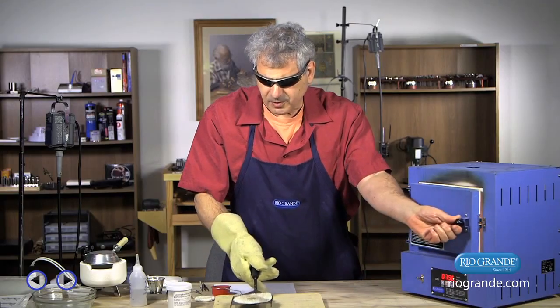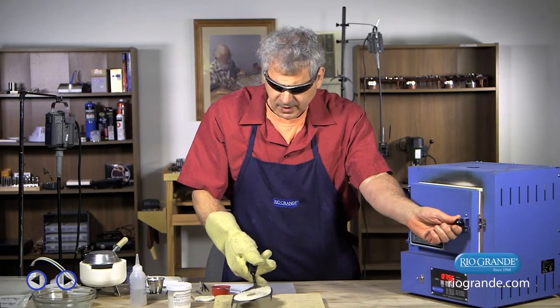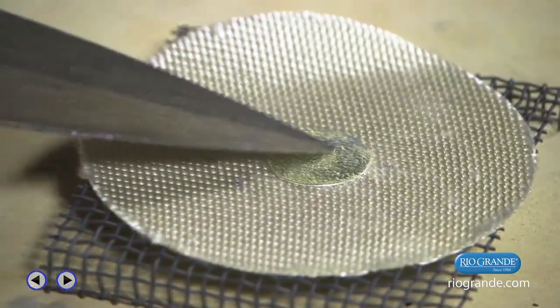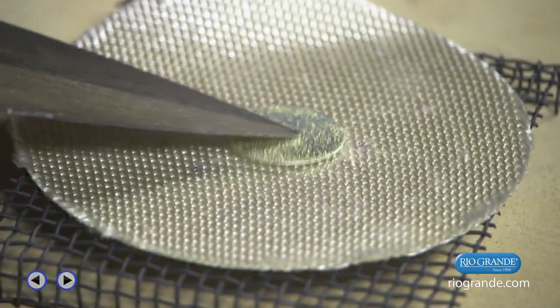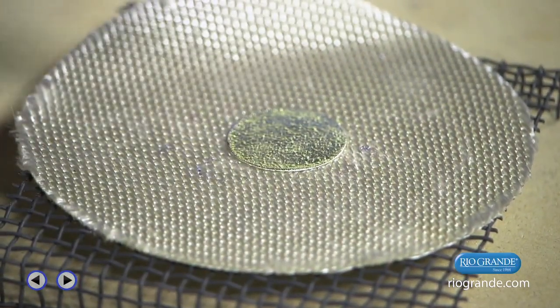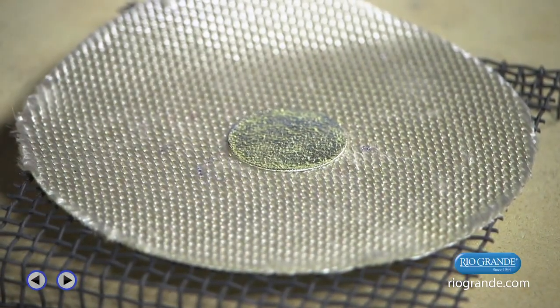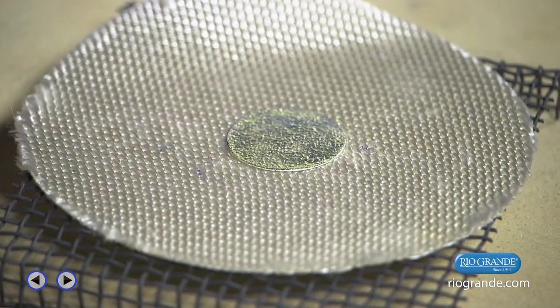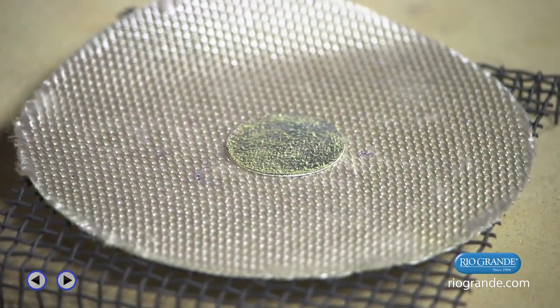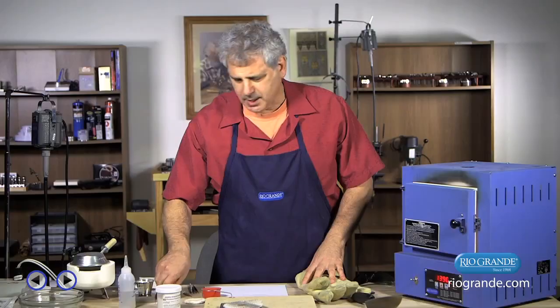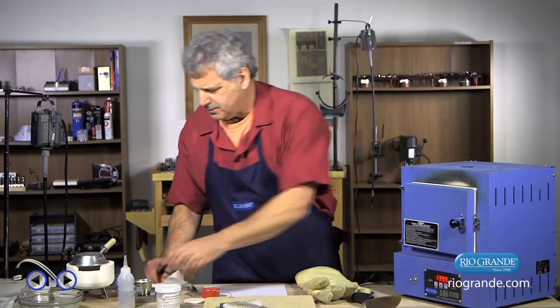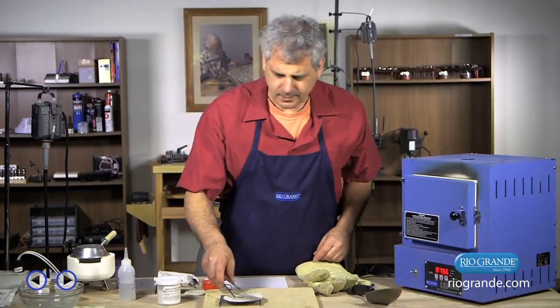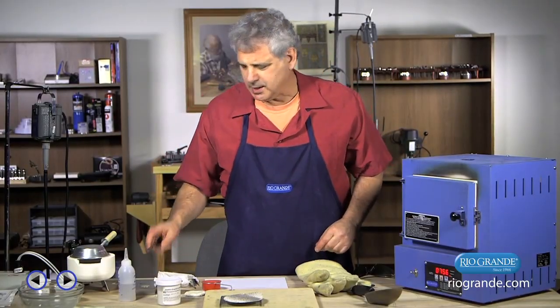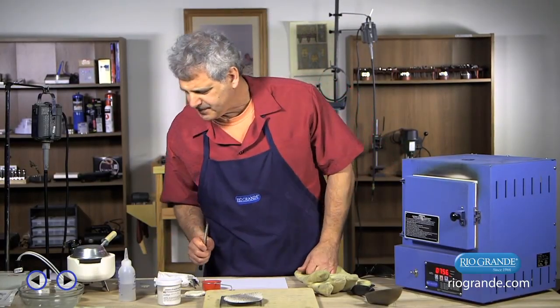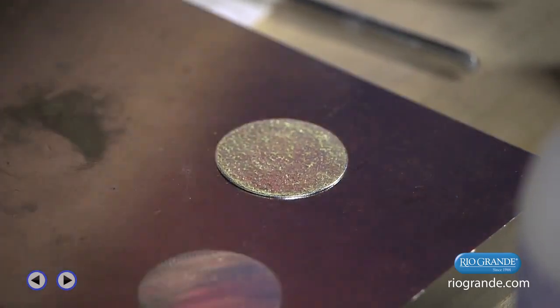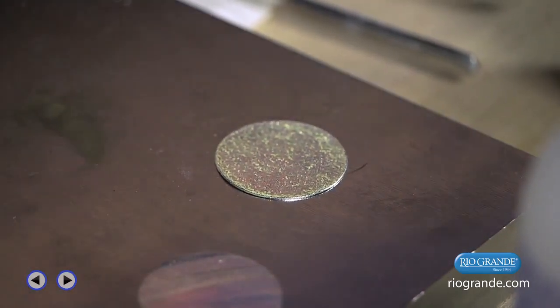It's almost perfectly smooth. There's a little bit of texture there. And if I run my trowel along here, I can see whether that texture is from the enamel or from the texture on the silver before I fired it. So we're going to let that be just right. And to cool it, I'm going to place it on this steel block and it will cool down very quickly. If I wanted to quench it, I could, but I would normally wait about 15-20 seconds so the enamel doesn't crack too much.